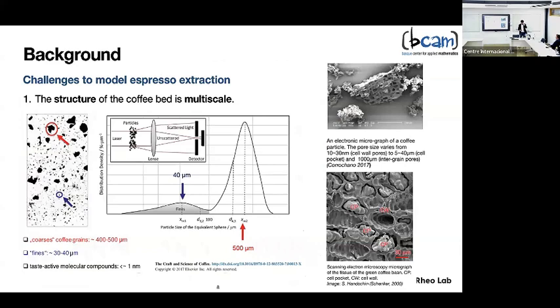This is a challenging problem to model, for many reasons. One is structural, the other is related to the complex physical processes that occur. From a structural point of view, the problem is fully multi-scale, and every time we model a multi-scale problem, we have computational and numerical issues. The multi-scale nature in coffee comes first from the powder, which has different sizes of grains, and almost all powders have a bimodal, or in some cases trimodal, distribution. The largest particles, in red there, are typically 400 to 500 microns. Then you have fragments, the so-called fines. In coffee jargon the larger particles are called coarses, and the smallest particles, around 40 micrometers, are the fines. There is already a scale separation of one order of magnitude between the two.